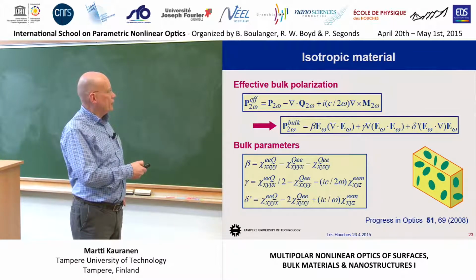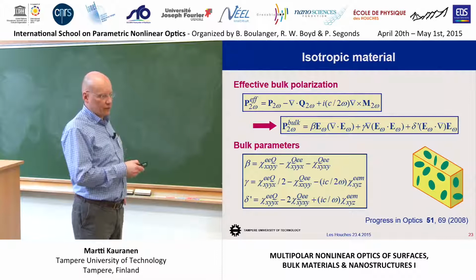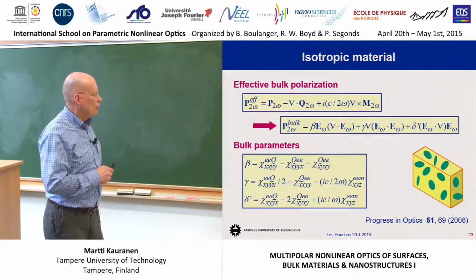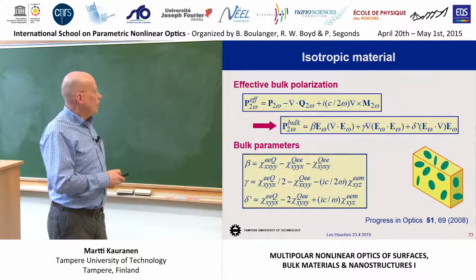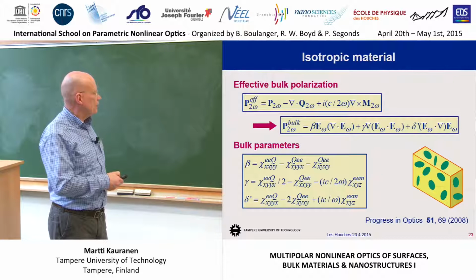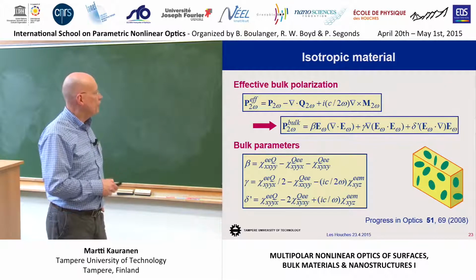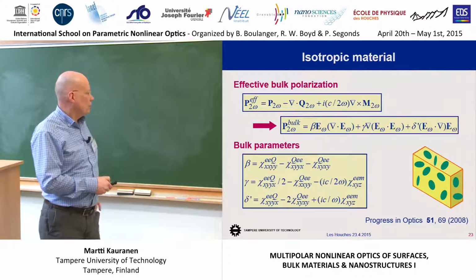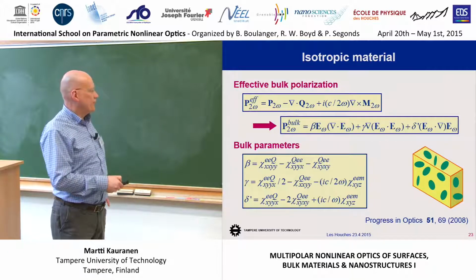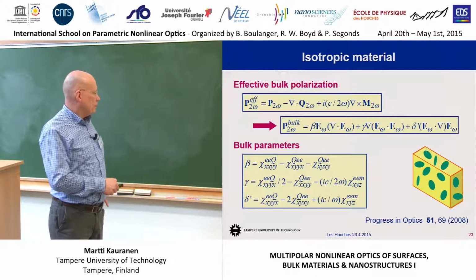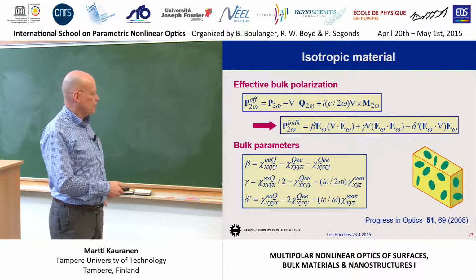There are three parameters: beta, gamma, and delta prime. The reason that you have a prime here is a historical reason, and I'll come back to this issue a little bit later. This beta depends on a certain combination of the components of the quadrupole tensors. So we have the EEQ, QEE tensor and certain components from there. Gamma depends on the quadrupole tensors and also this EEM tensor, which is also non-vanishing. Delta prime depends also on the quadrupole tensors and this EEM magnetic tensor.